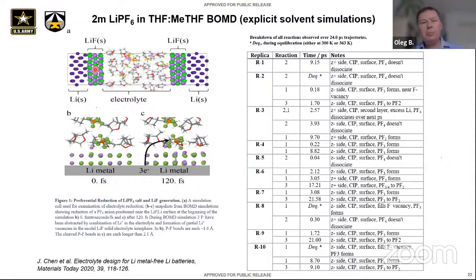The way we proceed with this, we understand that whatever initial configurations we have in this electrolyte is going to influence what reduction processes are going to occur. So we want to be accurate, and we developed an accurate force field within my APPLE&P framework. APPLE&P, by the way, stands for atomistic polarizable potentials for liquid electrolytes and polymers. So we use classical simulations to have LiF accurately representing the interface with electrolyte. We ran those simulations, in this case about 8 nanoseconds, and took snapshots.